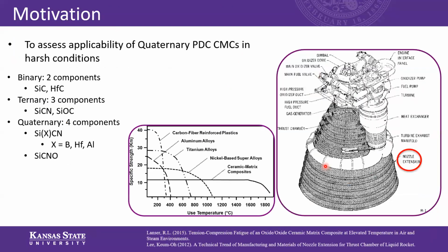So the motivation of the study is to assess the applicability of quaternary PDC CMCs in harsh conditions. The quaternary PDCs, specifically of SiXCN, exhibit exceptional structure and chemical stability at elevated temperatures. Previous research has shown that these materials remain amorphous at up to 1500 degrees C, have excellent creep resistance, and are stable to approximately 2000 degrees C.